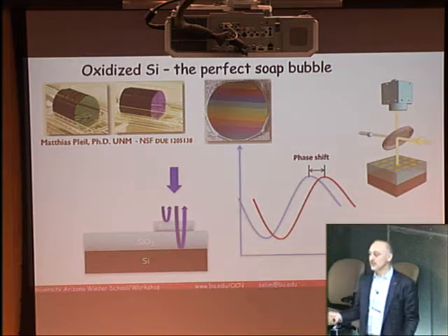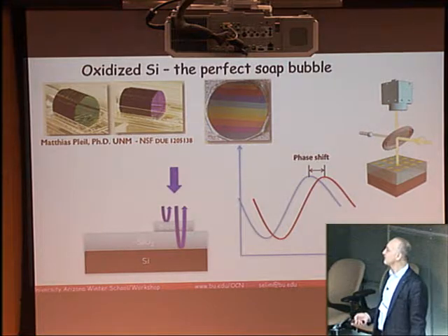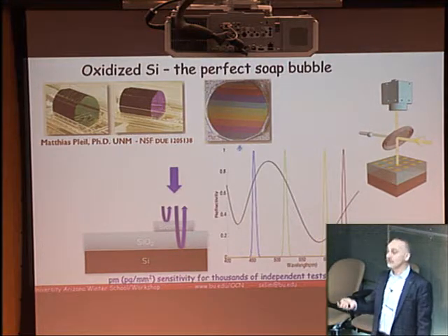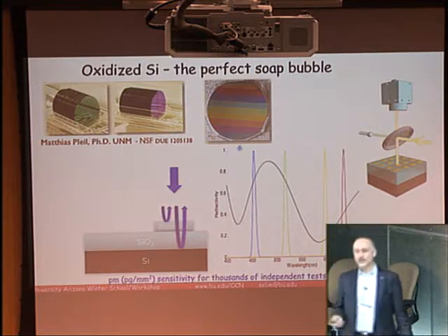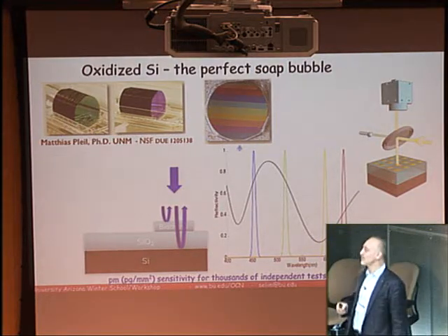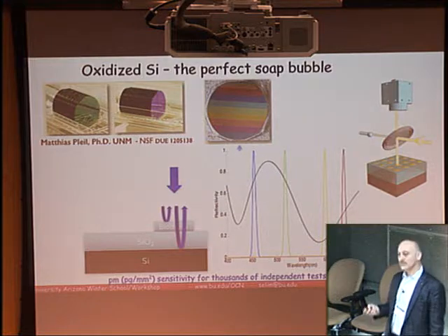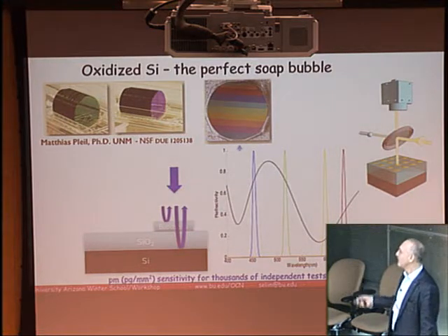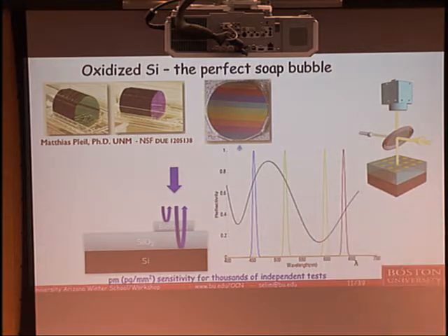That is the basic principle behind interferometric sensing. And you can do that, as I was corrected by my signal processing colleagues, without all these 20 measurements. You can actually do 3 or 4 measurements to fit a well-prescribed reflectivity signature. Now we know that we can actually monitor a single point once we establish the thickness in a narrow range. So this is the methodology we use for biosensing.